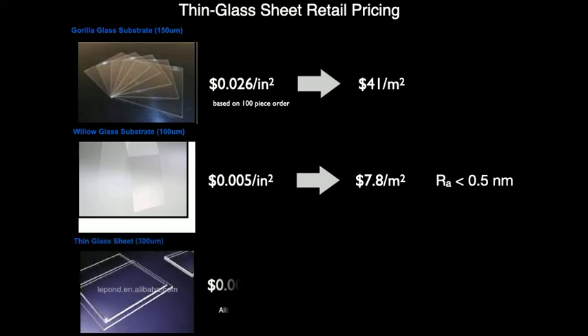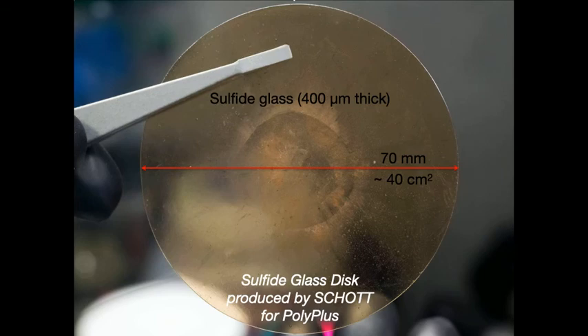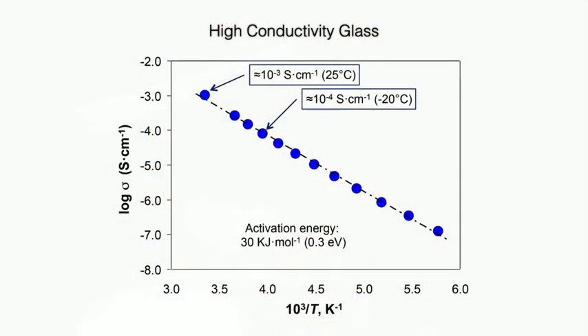And in China, you can get thin sheet glass for about $1 a square meter. So as I mentioned, we're working at PolyPlus with sulfides. You can see here, this is a 70 millimeter piece of glass that was actually pressed above the softening point. It's about 400 microns thick, and it's very conductive. You can see here the ionic conductivity as a function of temperature. So at room temperature it is 10 to the minus 3 Siemens per centimeter, which is quite high.